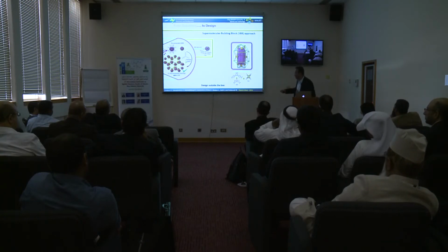So let's look. You have two sets of 120-degree angles, one set of 90-degree angles, and the copper paddle wheel. So if I have a ligand that has 2 times this and 1 time this, and I can make this all the time, and that's the only possible structure to form, I should be able to make this structure without a problem. So going through very tough organic synthesis with multiple steps, let's see if this can work.